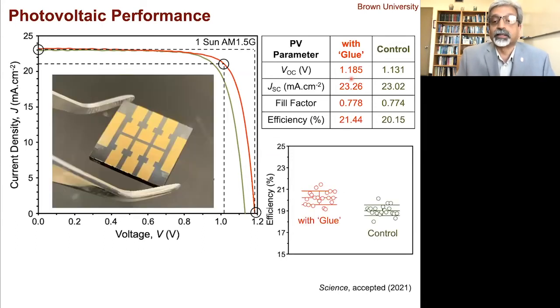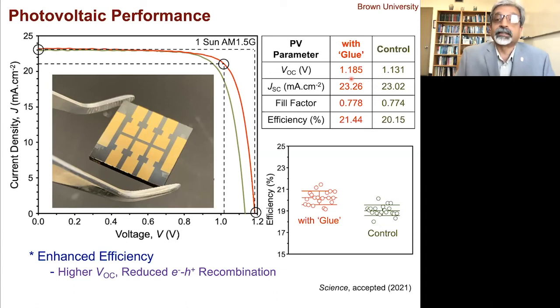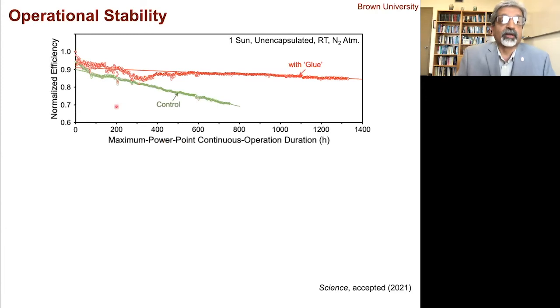And this is primarily, okay, so this is some statistics. We do a lot of solar cells to do this. This is actually a photograph of the solar cell. And this enhanced efficiency is primarily due to an increase in this VOC because of reduced electron hole recombination that the glue affords at that interface. So this is a functional glue, right? So now let's look at operational stability. So this is normalized efficiency. Again, I'm just presenting here one data set. We have many other data sets, and also I don't have time to present all the underlying science that went into actually making this happen. So this is normalized efficiency. As you can see, the control efficiency is dropping.